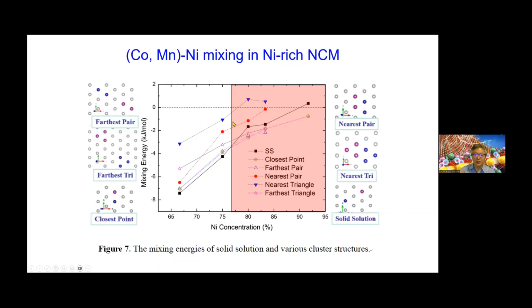If you look more carefully, this is full DFT modeling data. If you look at solid solution, then beyond 75%, the solid solution is less stable than clustering. So it's driving a rapid transition for this random alloy of nickel, cobalt, manganese in the nickel-rich mixture of the cathode material. When you increase the nickel concentration beyond 75%, those cobalt and manganese atoms tend to cluster and phase separate.